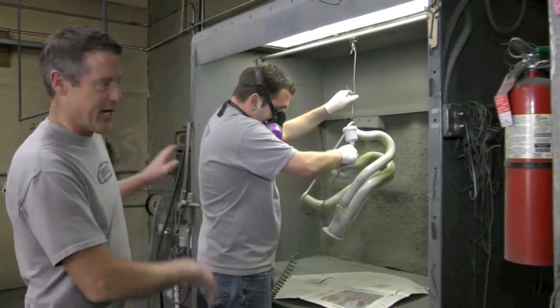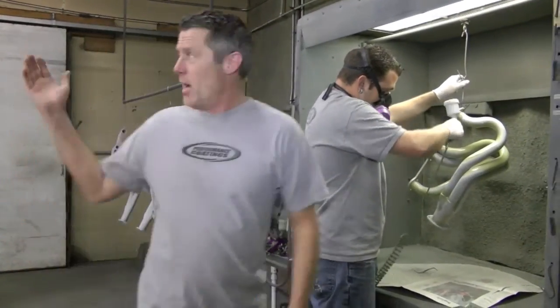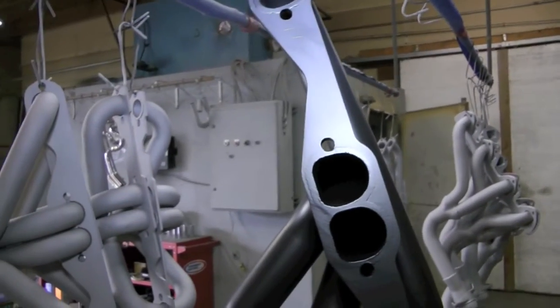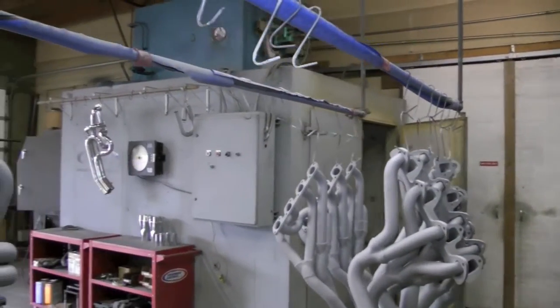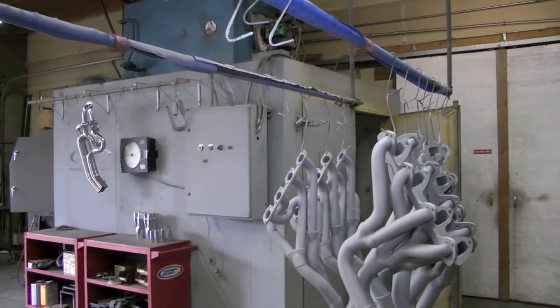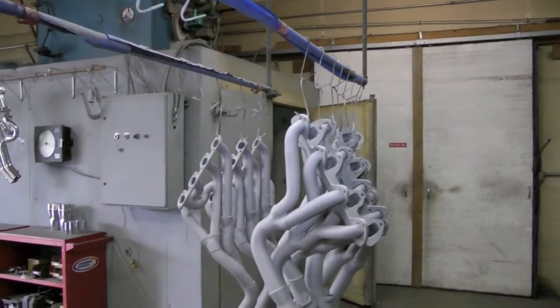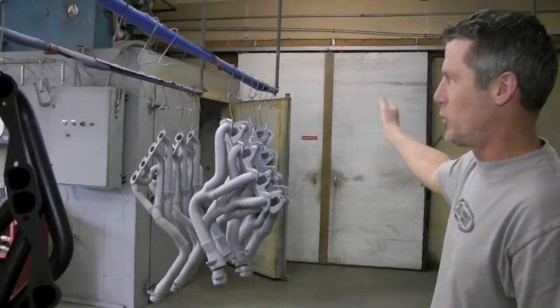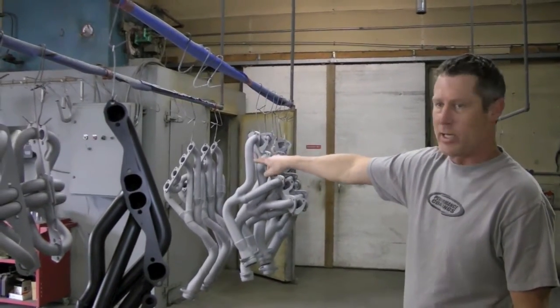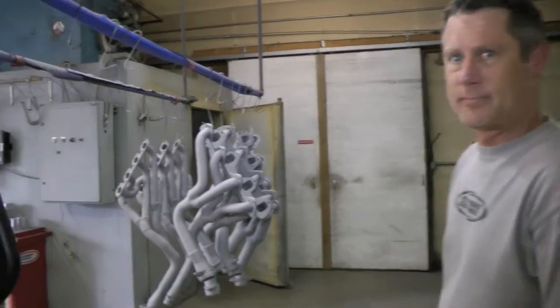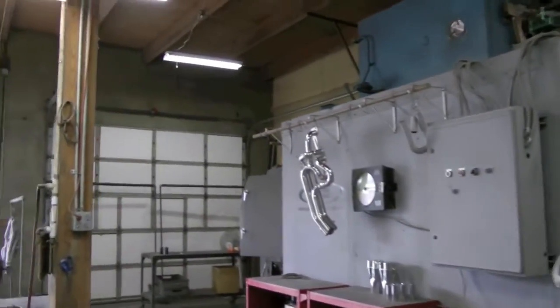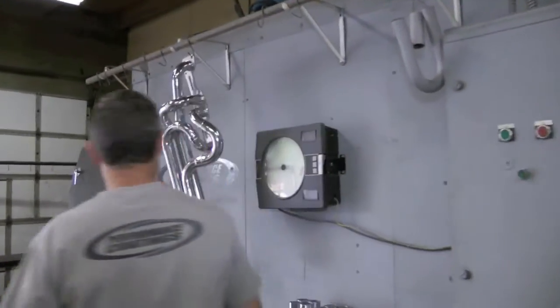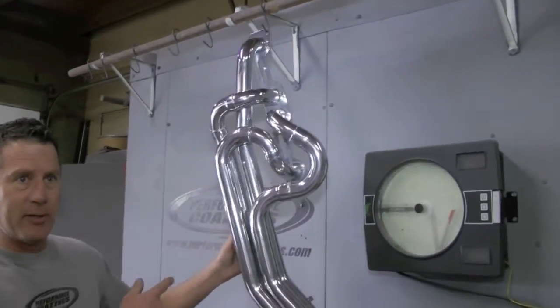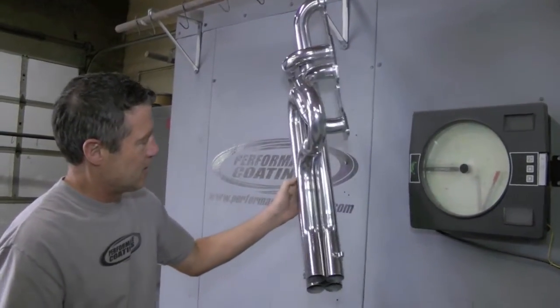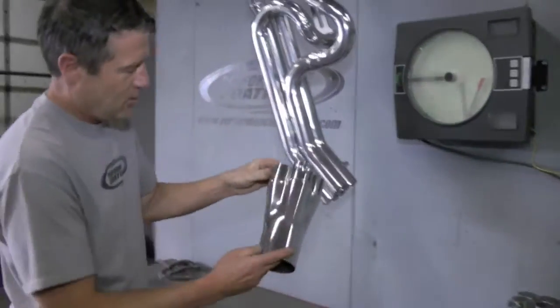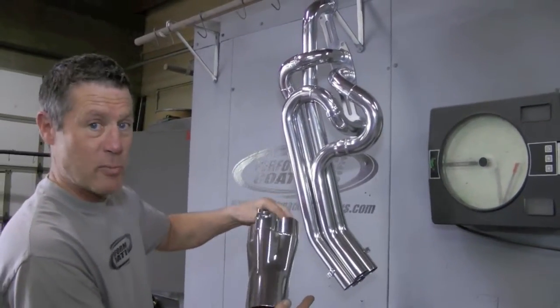This green coating is going to air dry white. We're going to throw it in the oven over here overnight, 500 degrees for 4 hours. Then we're going to take those parts back behind these doors and put them through a vibratory polishing process. And after about 45 minutes in one of those machines, they'll actually come out of there looking like polished aluminum. The end result of all the steps along the way: you get a highly polished, almost chrome looking finish, depending on how smooth your metal is.